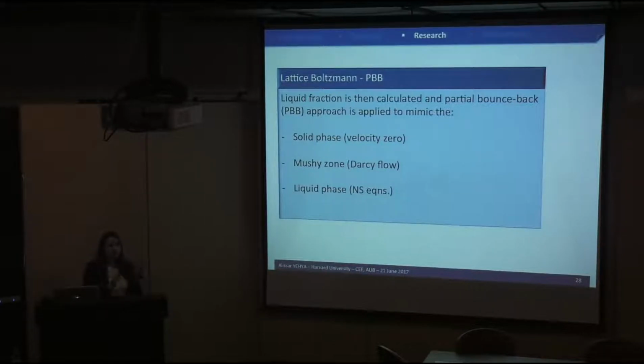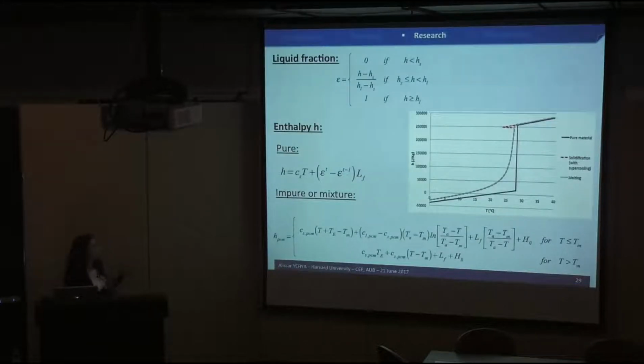a little bit in analogy with Voller's work in the enthalpy-porosity approach, where he treats the mushy zone as a porous material, and the liquid phase follows the normal Navier-Stokes equation. So to differentiate between these three phases, we use the liquid fraction. The liquid fraction is calculated from the enthalpy, and the enthalpy is related to the temperature through the enthalpy-temperature relationship. But as we said, this is the piecewise function that is usually known and used, which is symmetric and used for pure material melting and solidification.